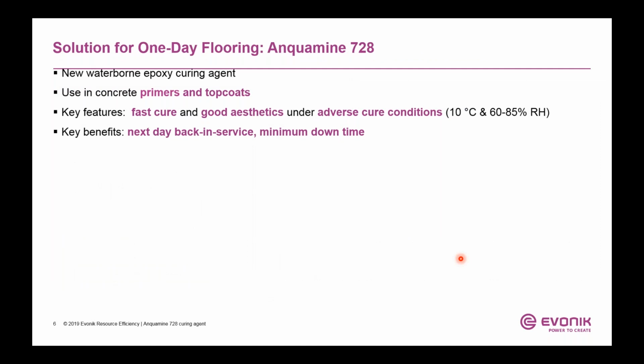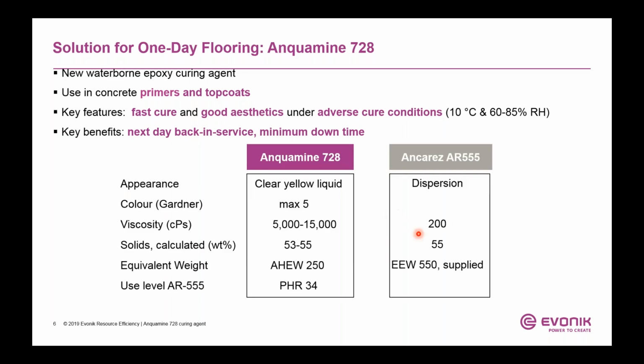Since we can't find a commercial system, we developed a new system. It's a waterborne system based on Anquamine 728. Anquamine 728 is a new waterborne epoxy curing agent that can be used in primer and in top coat. So it eliminates the inventory issue, where you have to stock different curing agents for primer and for top coat.